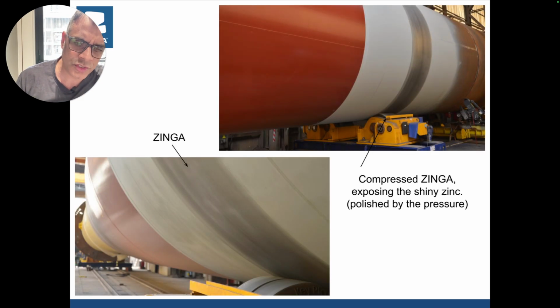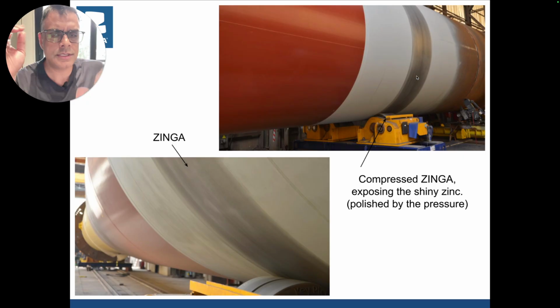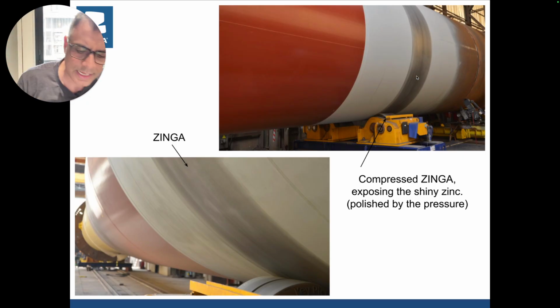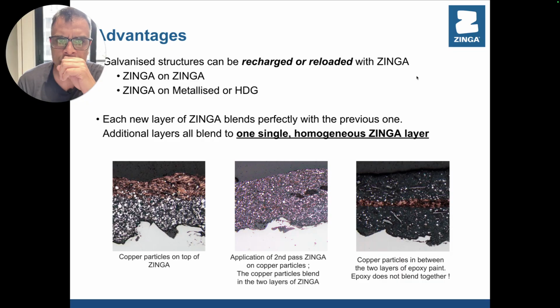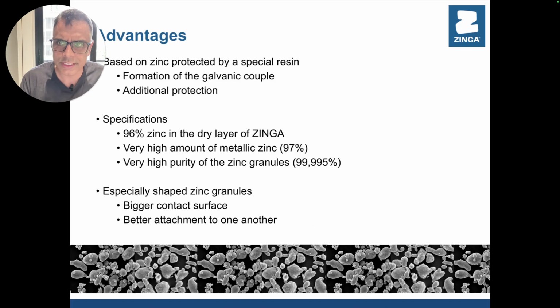You can see the sheer amount of stress the paint is going through, wherein on the rollers of these windmill turbines, you can see that the zinc oxide layer is coming out. So if I show my mouse here, zinc oxide layer has come out, but the active cathodic layer is still there. Galvanized structures can be recharged, so you can basically see here we are showing you a zinc layer, how it's forming a homogeneous layer. They are no longer distinct. With time, it becomes a single homogeneous layer.